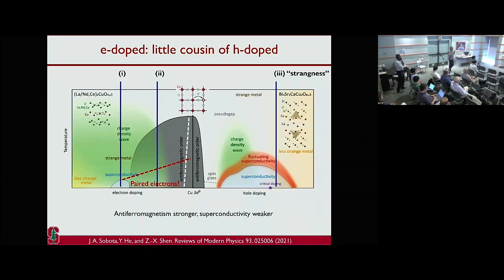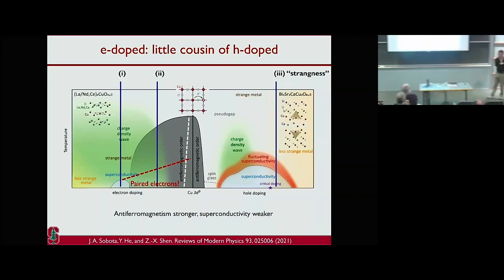And very quickly, the second part I want to say is that if you have precursors, and precursors come from thermal fluctuations, then of course if you look at the spectral function, you have a lot of spectral weight transformed from low to high energies. But if you solve for superconductivity, thermal precursors actually cancel out in the superconducting problem. As a result, you get exactly the same superconducting problem as if precursors didn't exist. So this is what I want to say. Thank you very much. It will be something we can look into.